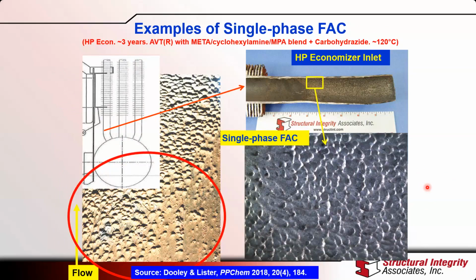Now here are two examples. So this is an example of single phase FAC. At the bottom here, an HP economizer. This is the inlet header at the bottom, and the geometrical feature here is this bend right here. Most typically, single phase FAC takes place in combined cycle plants which operate on AVTR. That means that a reducing agent, or you might call it an oxygen scavenger, is added to the chemistry. And this is the typical appearance that you see here of single phase FAC. We most often say it looks like an orange peel, the surface of an orange. And you can see on this one here, just around this bend, which has produced the geometrical feature, you get this appearance of single phase FAC damage.